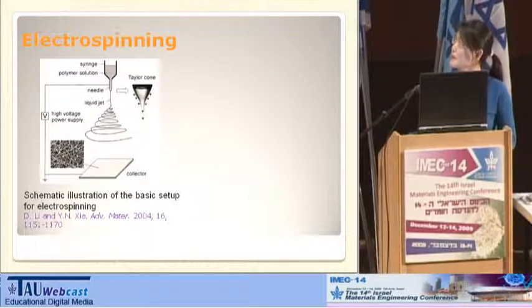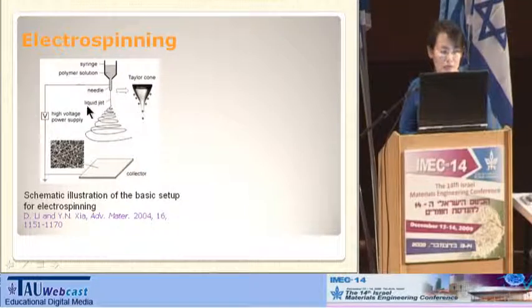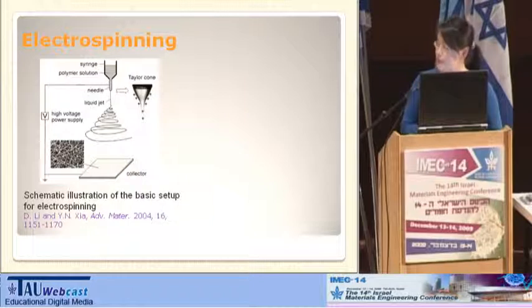This is a simple principle of electrospinning. We put a polymer solution inside the syringe, and then we apply a high voltage to the solution. In the strong electric field, a liquid jet will be ejected from the syringe nozzle, and then this polymer fiber will fly in the electric field, and the fiber will be stressed